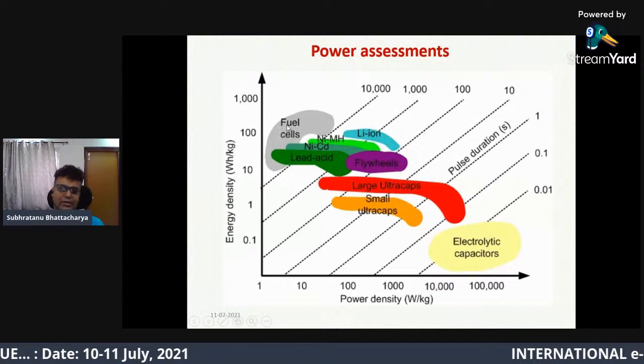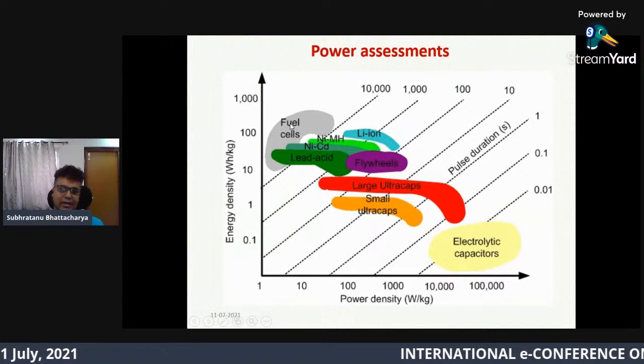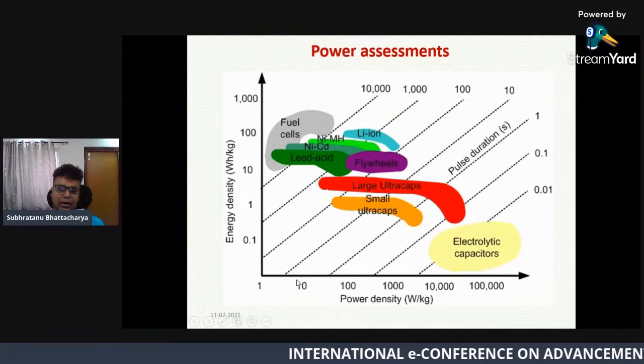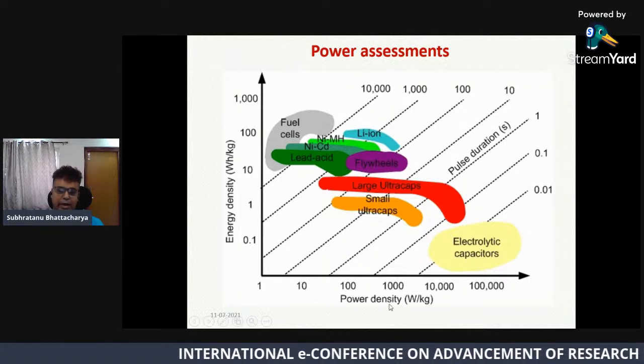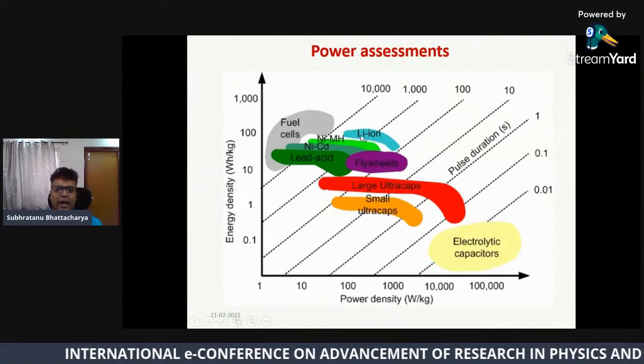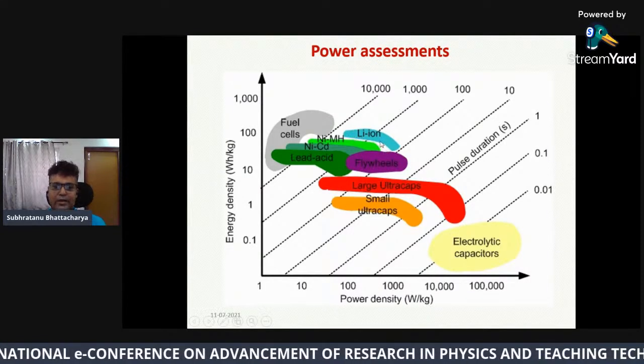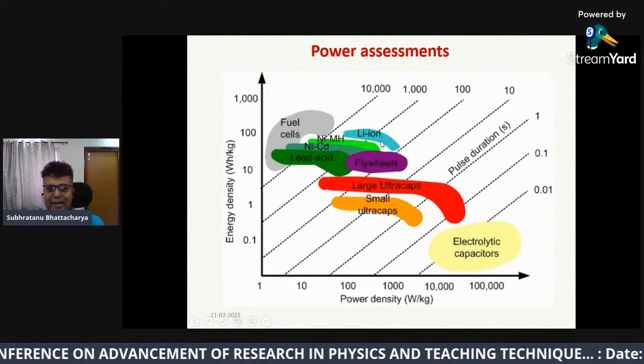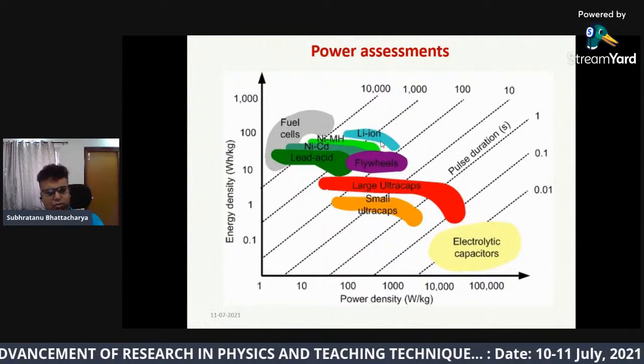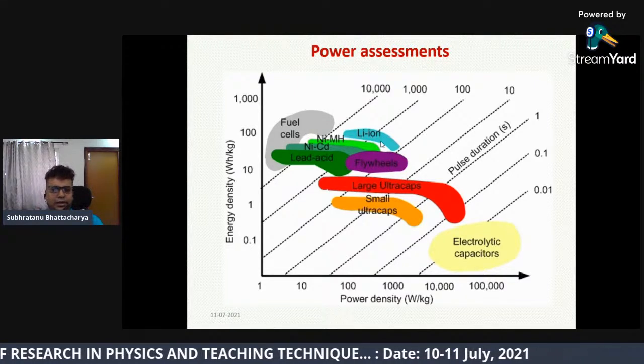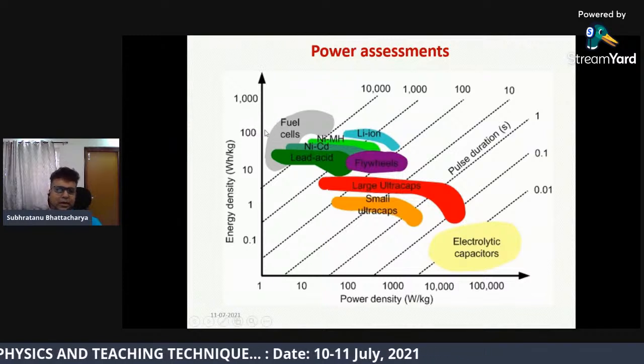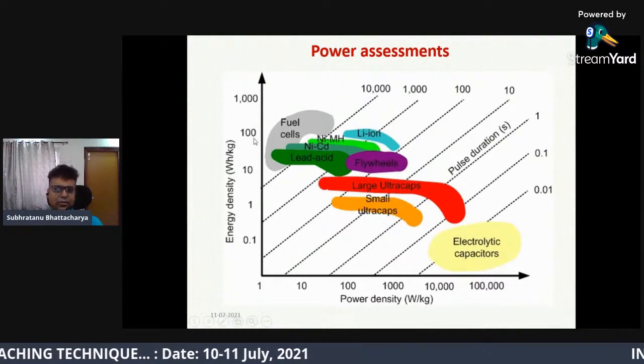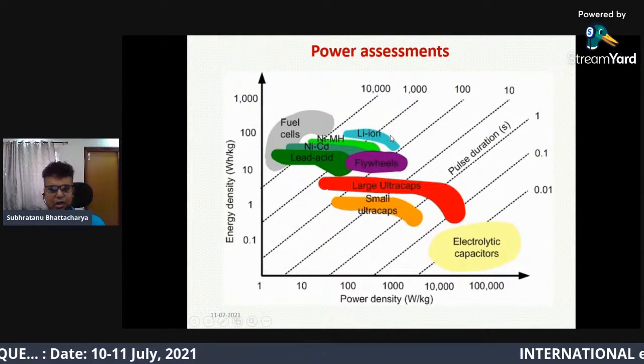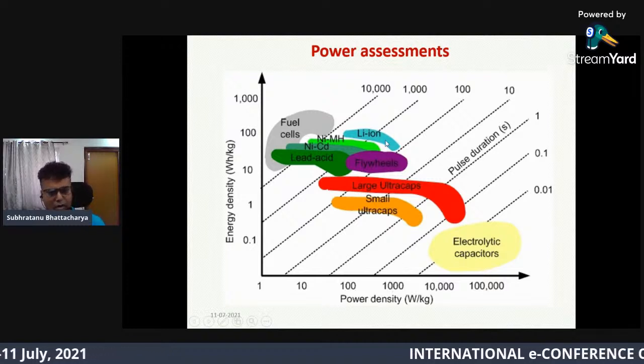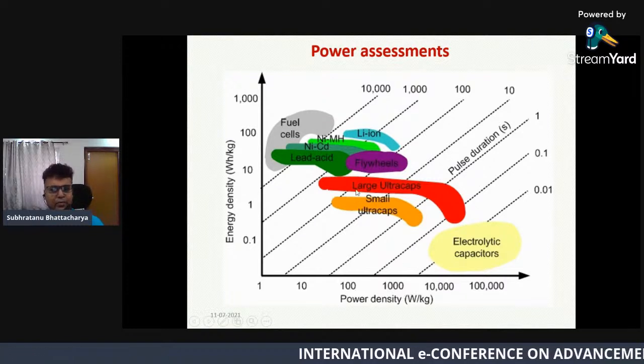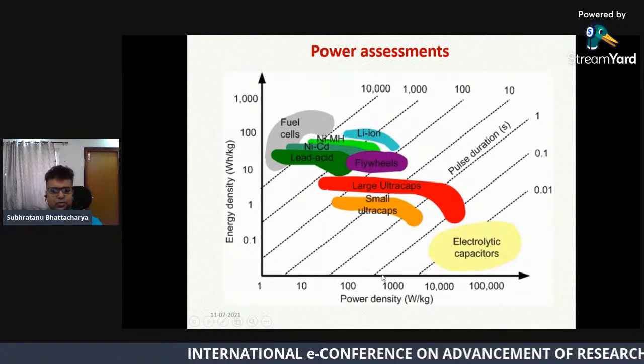You can see for the fuel cell, that is the high energy density device, it has only a power density of 10 watt per kg. And if you consider the lithium battery, it is almost a balanced factor. To some extent it is a better scenario for the lithium battery. The high energy density is around 100 watt hour per kg with a moderate, not very high, power density, like 10 to 1000.